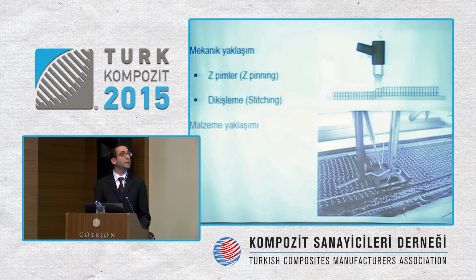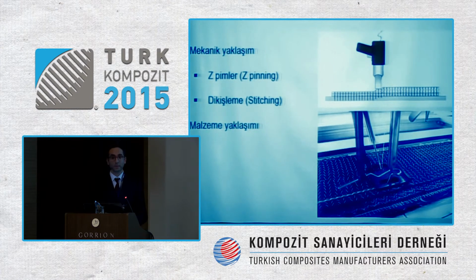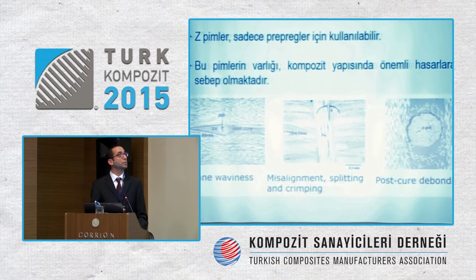And that's why we have improvement methodologies for fiber reinforced composites. We have mechanical approaches like Z-pinning and stitching. Z-pinning is applied before curing. An ultrasonic device is used, and the pins may be steel or composite. It is a pinning methodology, and this is only used for the pre-pregs, and the structure inside can lead to defects, for example, resin-rich related defects, or maybe misalignment, or in-plane waviness, or splitting and crimping.